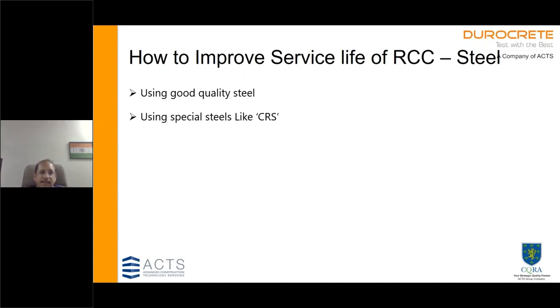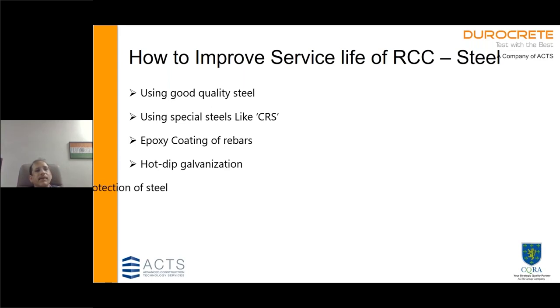There are special steels that are available, like corrosion resistant reinforcement steels that have a high amount of chromium, so that prevents corrosion. Then there are epoxy coated bars also available, but care has to be taken while using epoxy coated bars that no part of the epoxy is damaged, because if a certain portion of the epoxy coating is damaged, that can be sometimes very dangerous because it can lead to pitting kind of corrosion. Then these are for special structures. You can go for hot dip galvanization or cathodic protection of steel. Hot dip galvanization was used for the Baha'i temple.